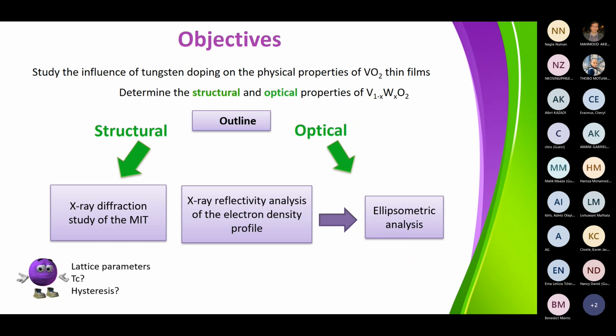Okay? And the first thing is that if you do X-ray diffraction, you are going to look at how the structure is evolving as a function of temperature. So you will get the lattice parameters. And if you look carefully at how the Bragg reflections are evolving, you can describe the hysteresis that you can find in this transition. The reflectivity analysis is very interesting for measuring the morphology of the film and typically the thickness of the deposited layer and the roughness of the interfaces.